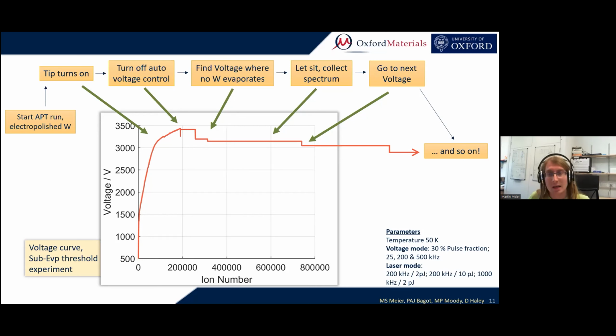fields. In particular, what we can then also do is repeat that entire experiment many times again with different parameters, like in laser mode and voltage mode, at different laser energies with different pulsing frequencies, and so on. All of this on one tip that never evaporates and that never changes geometry. And what this does is it gives us a set of very well matched and paired hydrogen spectra where we can really see what the relevant parameters are and what might possibly be going on in our tip.